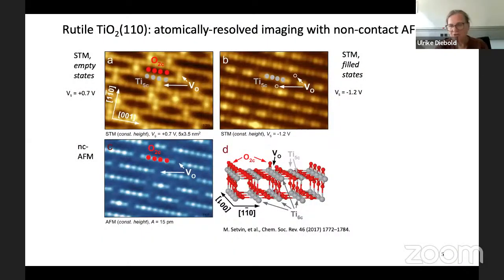So just a typical example. This is a material I've been working with a lot, rutile TiO2 (110). This is a density functional theory model of the surface. You would have surface oxygen atoms, titanium atoms, surface oxygen atoms. Some of these oxygen atoms are removed because of the way we prepare the samples, single crystalline samples, and then